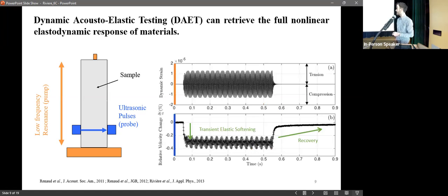All right, so if we do this in a rock sample, we get a very large nonlinear elastic response. So this is the pump signal, the strain measured using an accelerometer at the top, or we can also use a laser. When the strain is positive, the sample is being pulled apart, and when the strain is negative, it's during the compression phase. And what we see is that as soon as we activate the pump, the velocity, in blue here, this is the relative velocity change. If it is 0, the velocity doesn't change. What we see is that the velocity drops on average. So the medium becomes softer, and it's oscillating with the pump.